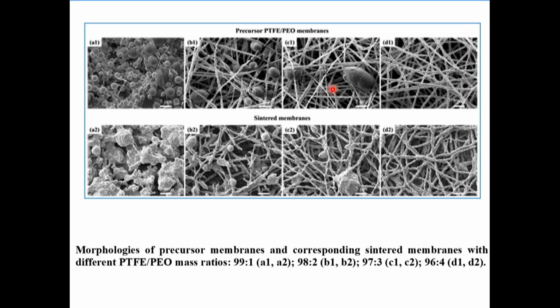So what kind of fibers do you get? Depending on composition, you might have fibers which are pretty ugly, fibers which are less ugly, but still, the beads are outside, so it's a disordered structure. But after all, you can end up with fibers which are pretty ordered, and after sintering, they are fully Teflon, and sintered beads provide a lot of roughness on the local level, so a lot of surface area as well. So this is essentially the type of fibers I'm going to talk about.